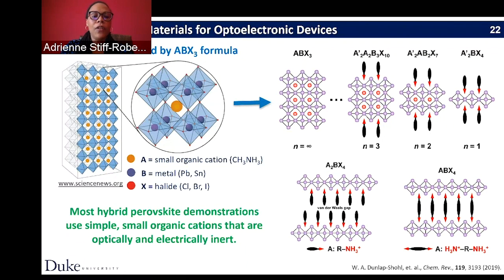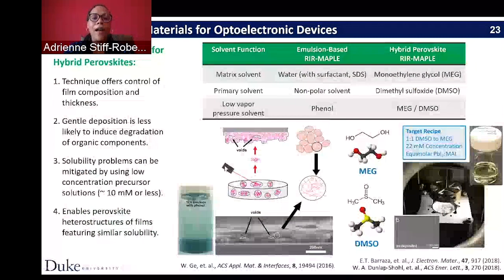And you can eventually get down to a situation where you have a single inorganic layer and a single organic layer. And so that is where MAPLE can come in, because those types of materials can be very difficult to synthesize by a solution process. So we did have to modify the target that we use in MAPLE to make them applicable for the hybrid perovskites, the big one being that you don't want to introduce water to these materials. So we had to find a new matrix.